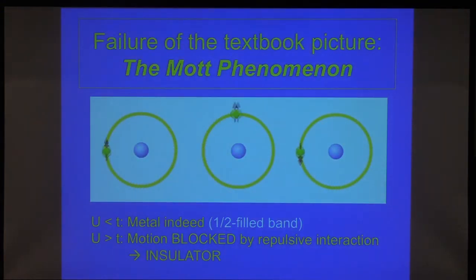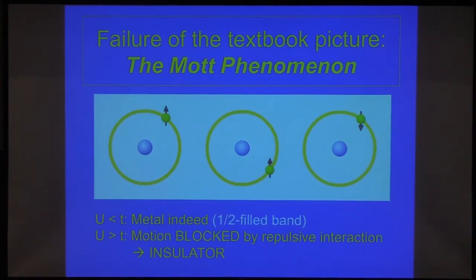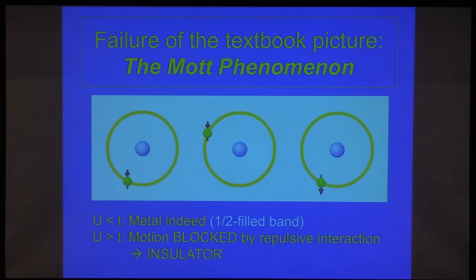Okay, so this is my cartoon picture, but now with a little bit of animation. What you see here is electrons that try to hop from one side to the other to form a Bloch band, but are prevented from doing so by the strong on-site U. And you would expect that when U is small, you can form a metal and delocalize the electrons and have a Bloch band. But when U is large, this is not possible, because the motion of the electrons is blocked by the repulsive interaction, and then you have an insulator. This is called a Mott insulator.